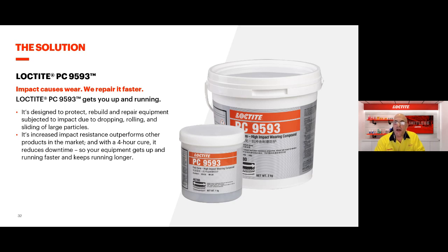Another example too is what they call, technical term, blowouts, where you may have a pipe which is worn through and you've now got water leaking or slurry leaking or coal dust leaking in a power station or a coal mine or a CHPP, and you want to put a quick patch on something just to get you through to the next shutdown in 4 weeks' time or whatever. You can apply this on the outside of the pipe to block that hole and create a bit of a wear barrier on the outside to prevent that hole from blowing out even worse. So it's got applications both inside equipment and outside.